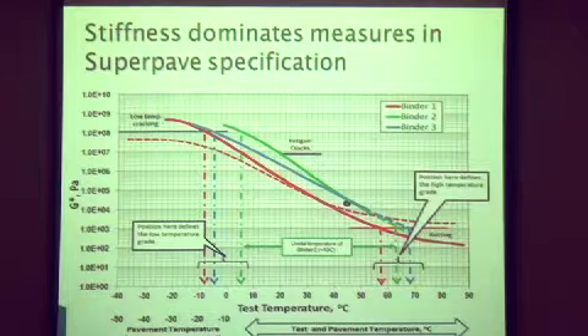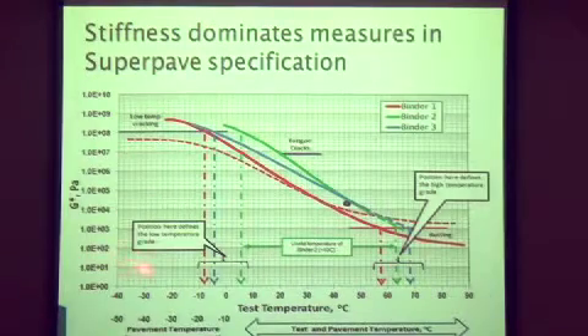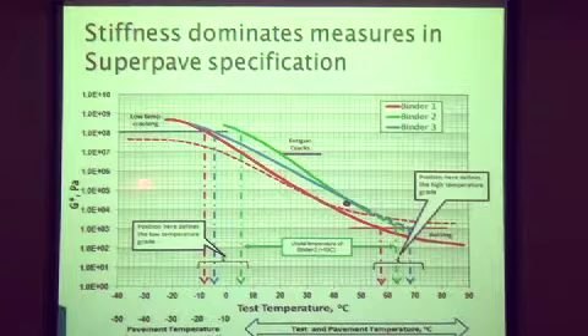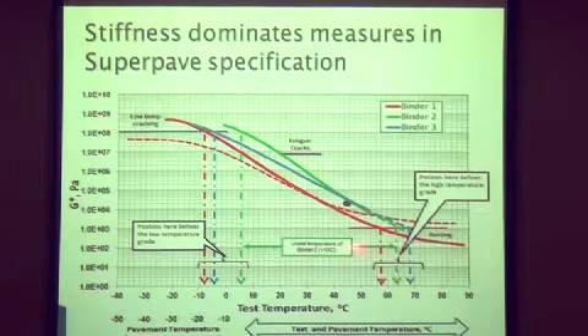Stiffness really dominates our specification. What I show here is some different lines of typical binders. We have temperature on the horizontal axis and a stiffness modulus on the vertical axis. Here the stiffness modulus I put is G*. The low temperature cracking criteria is shown here. The high temperature criteria for rutting is shown here. If you take a binder like this green binder here, it has a certain performance window. Okay? Now you can go and modify that binder, and the blue might be one of the modifications of that binder, and you can increase the performance window by modification.